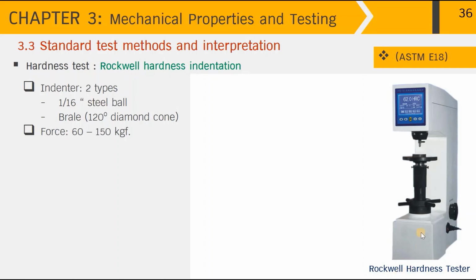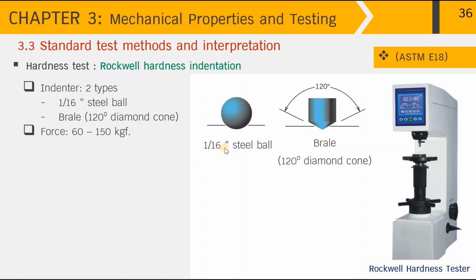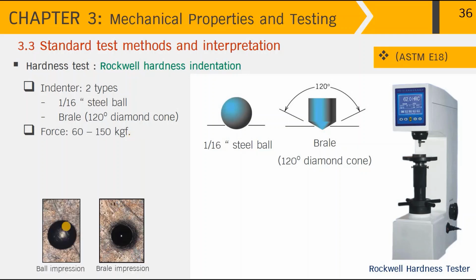Over here, you see the Rockwell hardness testing machine with the specimen set up down here and the display. There are 2 types of indenter. The first one is the steel ball having 1/16 inch diameter, and the second one is the diamond cone, and we call it the Brale indenter, having the included angle of 120 degrees. When we apply the force ranging from 60 to 150 kg force, depending on the scale of the hardness, we then have the impressions on the metal surface.